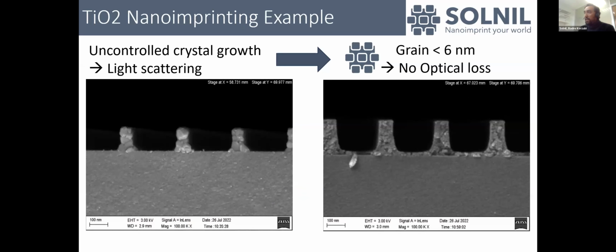So here are some SEM pictures of gratings we obtained with our process. On the left is standard sol-gel, which is not controlled. If you don't control the crystallization, you end up with very big crystals, like you see on the left, which will cause a lot of scattering and loss. What we achieve at Solnil is that we managed to control this crystal growth to have a very dense layer with no scattering by keeping the crystals below 6 nanometers. This is the key to achieve the refractive index and optical quality.